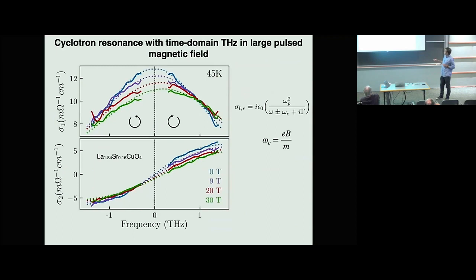This is a plot of the real and the imaginary parts of the conductivity as a function of frequency, plotted for right polarized light on the positive side and left polarized light on the negative side. The light blue is the data at zero magnetic field, and it's just a symmetric curve around zero frequency. We apply a field to it, and we can see that the maximum moves to the positive frequency side, and we can fit the real and the imaginary parts at the same time to the simple model to extract how that peak moves as a function of increasing magnetic field all the way out to 30 tesla. So really a remarkable thing. This is a completely new regime for being able to do optical spectroscopy.